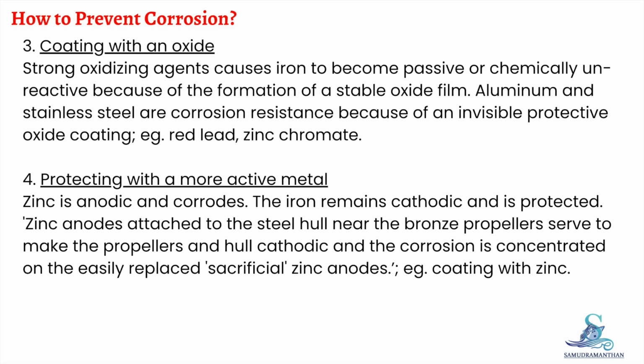Another very effective method is protecting steel with a more active metal. In this case, zinc is used, which is anodic and corrodes preferentially. The iron remains cathodic and is therefore protected. This principle is widely used on ships, where zinc anodes are attached to the steel hull near bronze propellers. The corrosion is concentrated on the easily replaceable sacrificial zinc anodes.